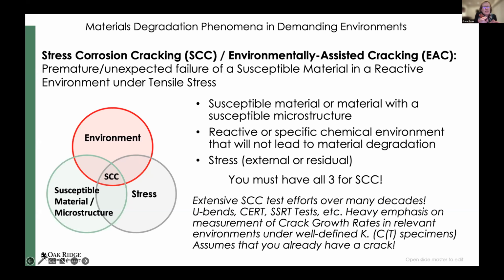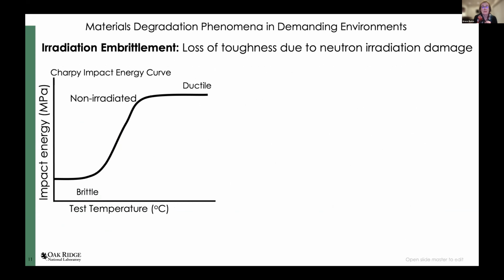Then there are lots of special tests that can be done to measure crack growth rates and the like, but we're not going to be talking about that at the moment. But the second part of the talk, when I get into the actual research, will deal with irradiation embrittlement, which is a loss of toughness due to neutron irradiation damage in the material. So I'm going to show a Charpy impact transition temperature curve. We have small specimens, and what we have is a function of test temperature. Our material goes from being fairly brittle with low impact energy to a fairly ductile failure at a higher impact energy. So this is our non-irradiated.